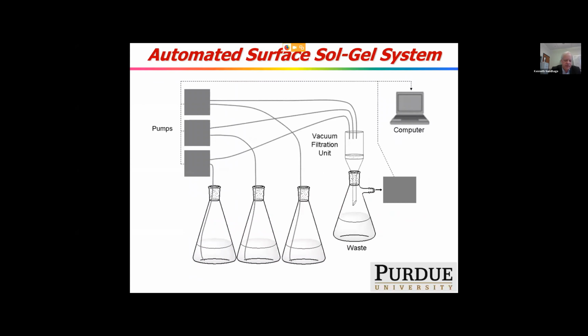So one of my students, Phil Brook, a very clever student, developed an automated process for doing this, to put many layers down. So we put the pollen over a porous ceramic frit, turn a computer on, pump in alkoxide for a certain time, then wash away the unreacted alkoxide excess, introduce water to rehydroxylate the dangling alkoxides, and then dry, and we can do this over and over again. Turn it on, come back the next morning, and have hundreds or thousands of layers.